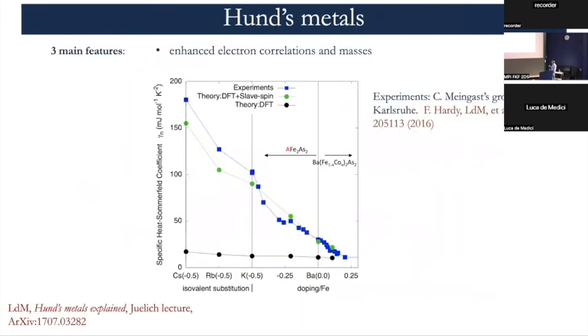So what happens is portrayed, for instance, by these experiments. Here we're plotting the Sommerfeld coefficient. So it's telling you how renormalized is the density of states. And when the Sommerfeld coefficient is high, it means the system is very correlated, or at least the bands have a high density of states. Here we are going through the same phase diagram, from barium to potassium, and then substituting potassium isovalently with rubidium and cesium, which are larger cations and basically decrease the bare bandwidth, so correlate the system even more.